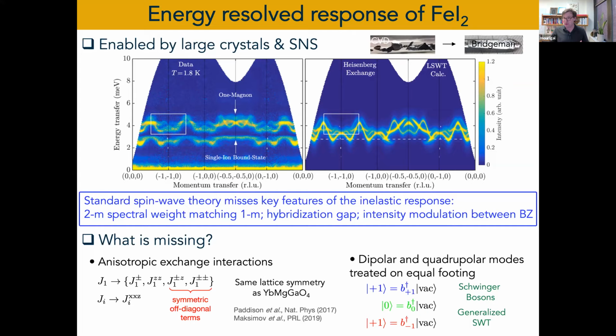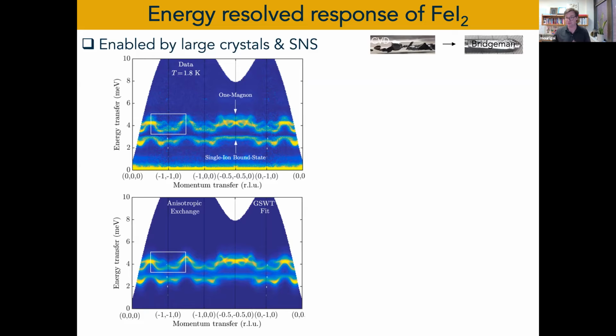And this is the amazing work that Christian and his group did, which is to generalize the problem using Schwinger bosons to having dipolar and quadrupolar fluctuations on equal footing. So essentially, you represent these plus one, zero, and minus one states with three types of bosons. So you constrain them in the traditional Schwinger boson way, and you plug in the Hamiltonian and you try to fit the data, and this is what we get. Okay, so this is after fitting and optimizing of these parameters.